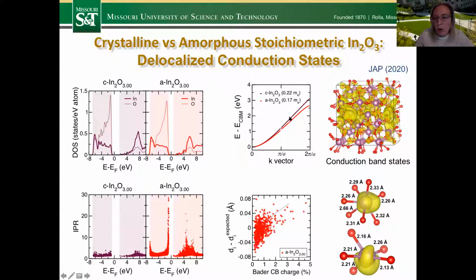And here we can plot even the bottom of the conduction band. We still have the parabolic conduction band similar to the crystalline materials. Effective mass is actually slightly even smaller in the amorphous case. And that is the first explanation why the mobility remains so good as we go to the amorphous phase. Here on the side, sorry, I keep switching because of my mouse, the conduction band states are shown. So this is the charge density only in the conduction band.